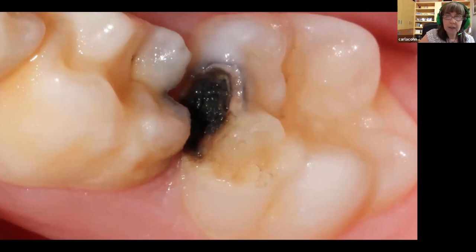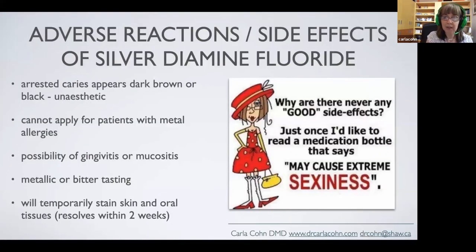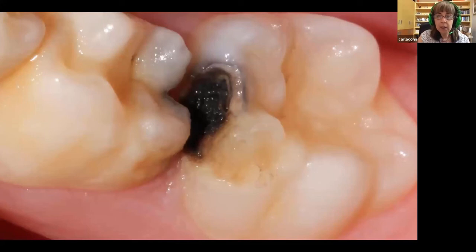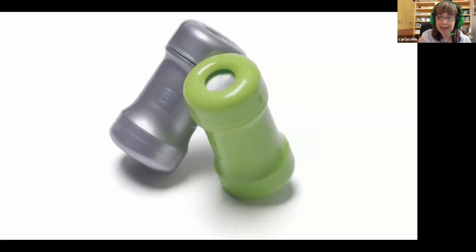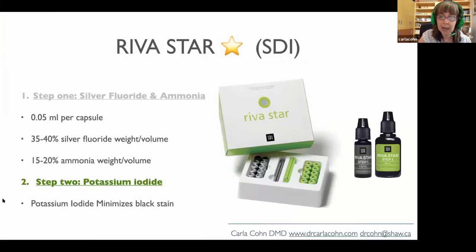If we're just placing silver diamine fluoride on our tooth's affected dentin, we're going to have a blackened area. So this is one of the adverse reactions of silver diamine fluoride, is that arrested caries appears dark brown or black. That's not aesthetic. We can't place it for patients with metal allergies, and we have possibility of gingivitis or mucositis. It tastes quite terrible, and if we do get it on skin or oral tissues, it will stain. That resolves within 2 weeks. So what to do about this darkened, unaesthetic looking silver diamine fluoride scar is SDI has come up with Riva Star with the addition of potassium iodide. That potassium iodide, as I said, minimizes the black stain.